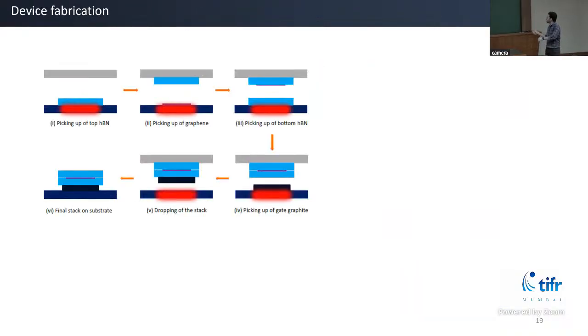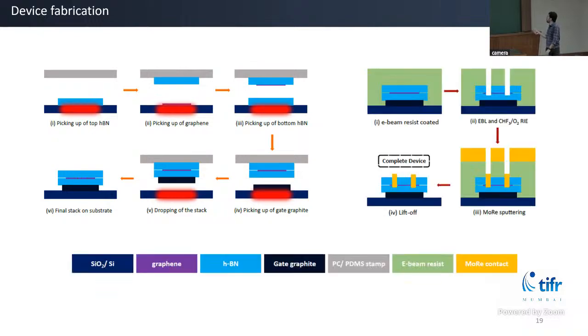So the fab step is similar to the heterostructure preparation in 2D materials. We pick up the layers one by one and then do standard electron beam lithography. We coat the electron beam resist that acts as a mask, then etch out the top hBN. And then through that, we deposit these superconductors using sputtering. So now this is our Josephson junction. This is one superconductor, this is a normal weak link, and this is another superconductor.